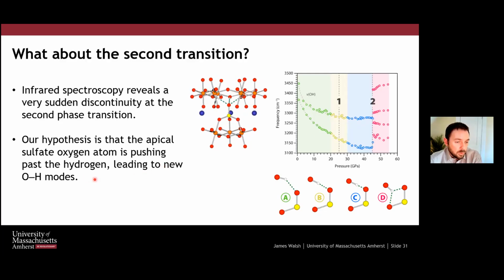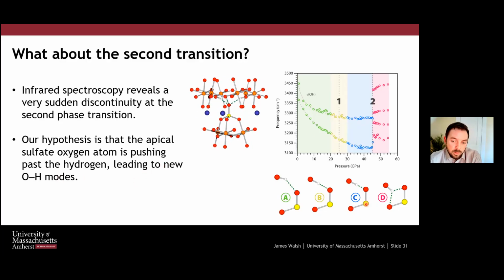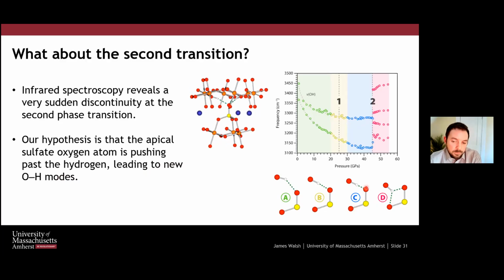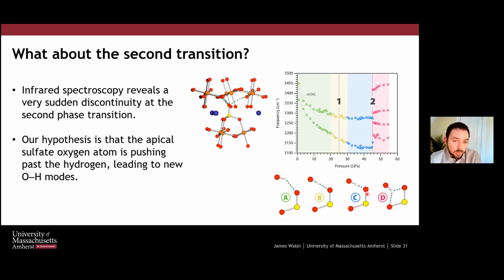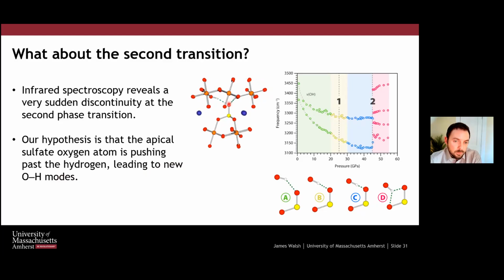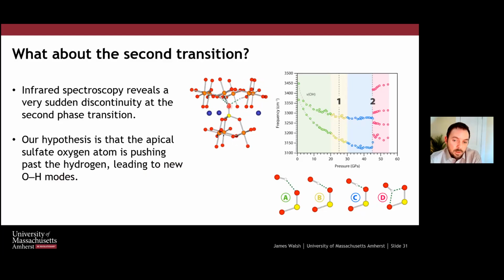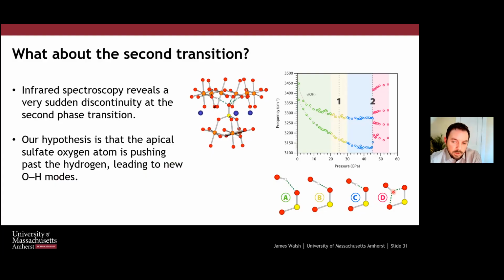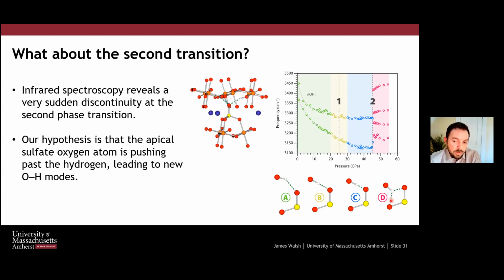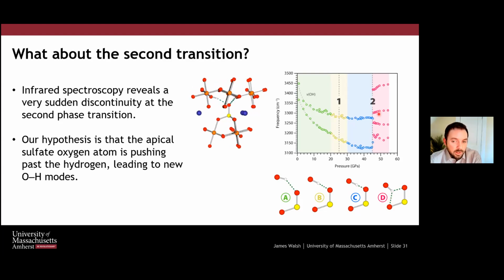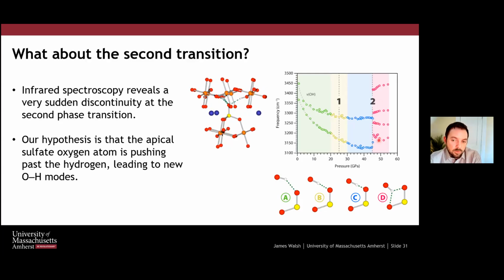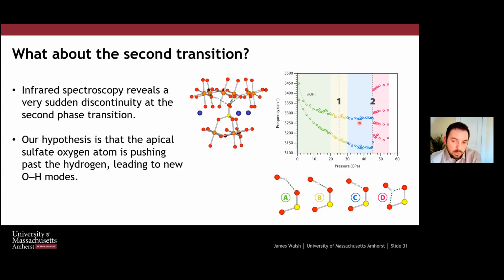And so our hypothesis is that at this point, we are moving the apical oxygen from the sulfate group, it's this oxygen in this rotating picture, we're moving it past the hydrogen in the OH group in the layer above. And that would then generate, we expect, two hydrogen modes where we used to only have one, and that is consistent with now having four modes in the OH region where we used to have two.